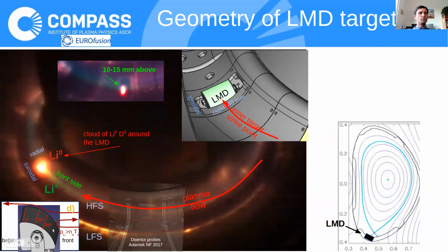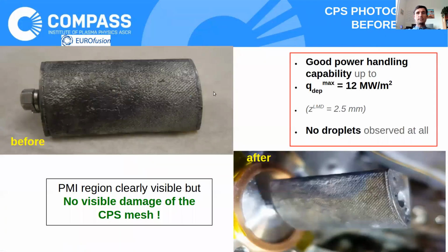And once we put it deeper into the plasma, the pressure of lithium increases above the plasma pressure, because the temperature of the surface increased strongly. We see that the lithium penetrates in front of the target, which is visible by the camera. Here you can see the photographs before the experiment and after the experiment.